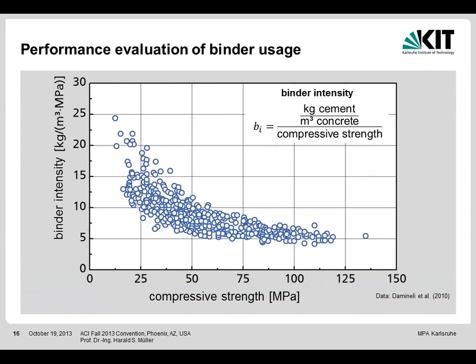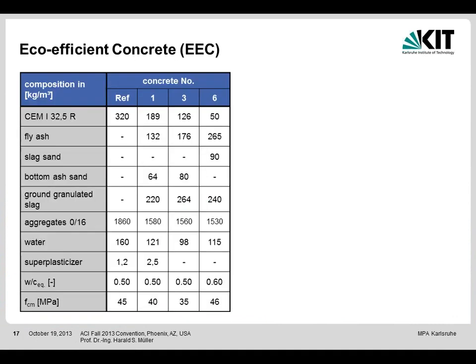I focus now on high strength concrete, ultra high strength concrete, and also what we can do with the low strength concrete. So if we produce an eco-efficient concrete, they may be composed as we showed for concrete number 1, 3, and 6. You have here the reference, for the average content of cement of the concrete, 320 kilogram per cubic meter. The aggregates, the water cement ratio 0.5. You end up with a compressive strength of 45.